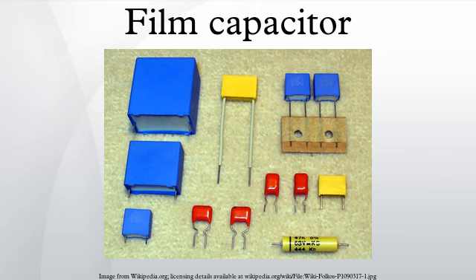Polytetrafluoroethylene film capacitors feature a very high temperature resistance up to 200 degrees Celsius, and even further up to 260 degrees Celsius, with a voltage derating. The dissipation factor of 0.10 to 0.4% is quite small. The change in capacitance over the entire temperature range of +1% to -3% is a little bit higher than for polypropylene film capacitors.